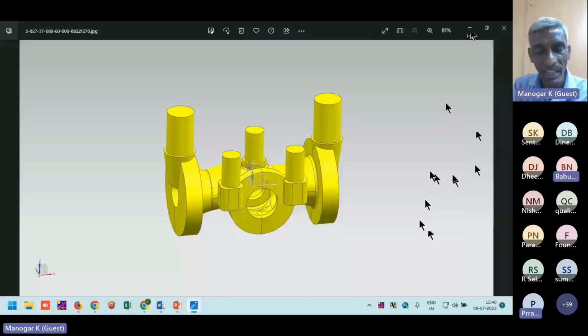But for smaller castings, where the casting is thinner, even 0.5 times the diameter works as height, where not so much feed metal is required. But a riser is required, especially in SR heat resistant steel castings. For the junctions, we can keep a smaller height also. In case of exothermic, not sand riser, people are using a 1:1 riser ratio.